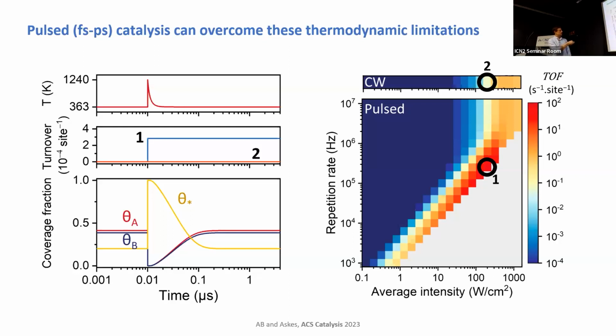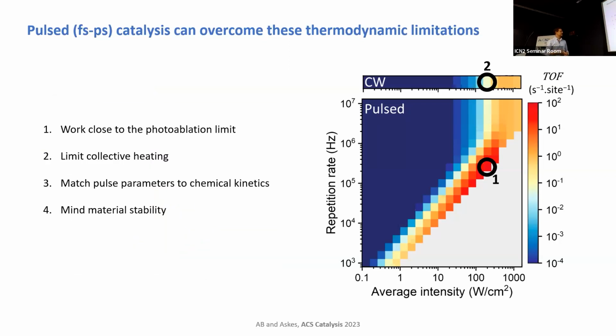So this is the amount of overall product that we form in the pulse regime over one pulse, and this is the amount of product that we form in the CW regime. So the difference is striking, and so we can form a much, much higher amount of product if we pulse it, and if we tune it properly. And of course, this tuning is crucial, so you have to work pretty hard, pretty close to the photoablation limit. You will see that the advantage with respect to the CW is typically on the right side of these plots. And here, this region is where essentially we photoablate our catalyst. So we need to be pushing the catalyst quite hard.